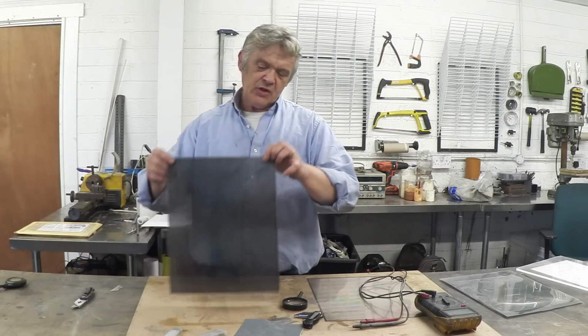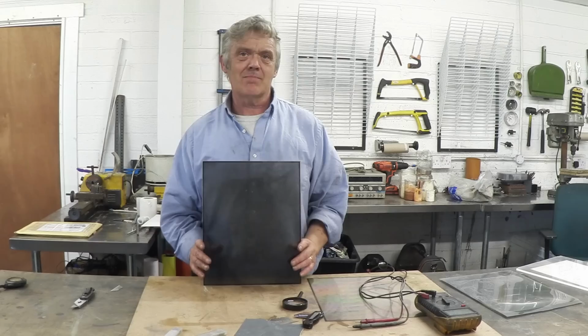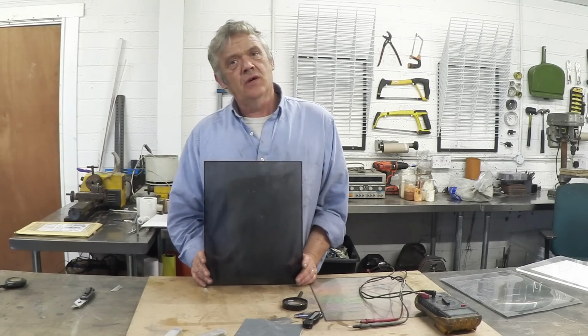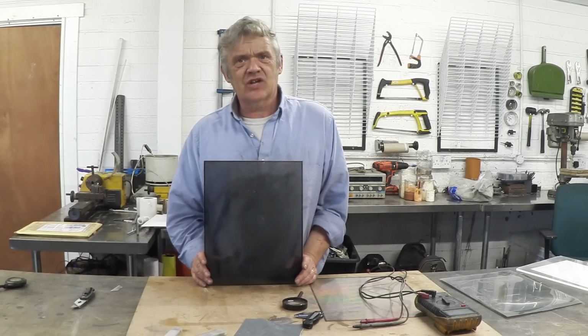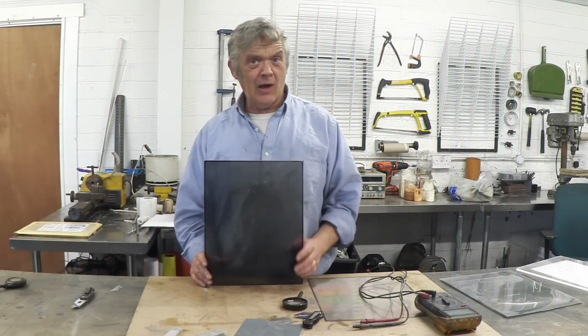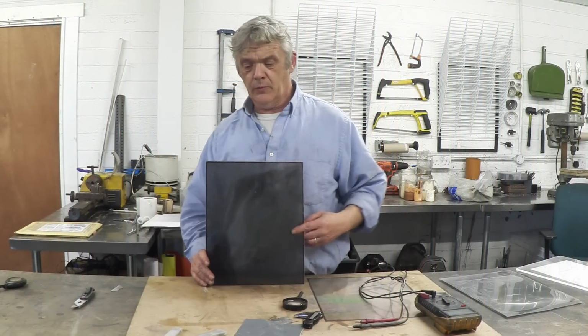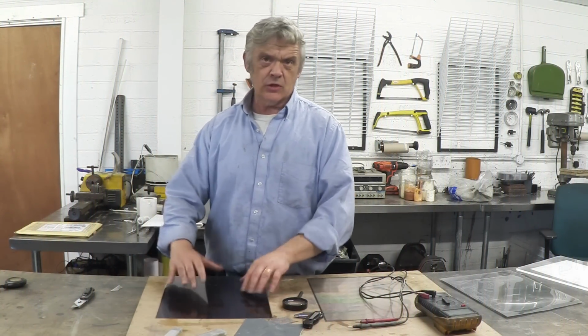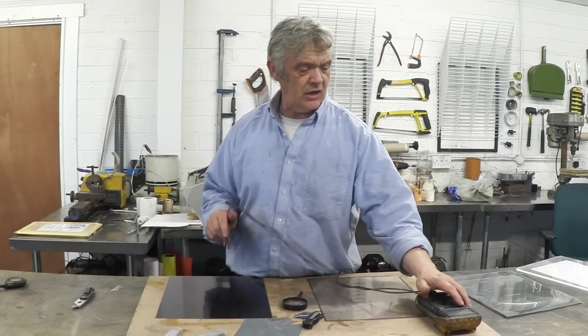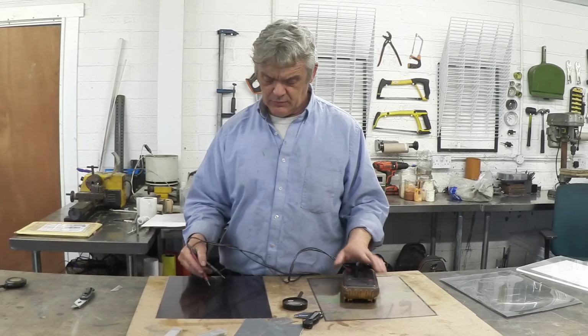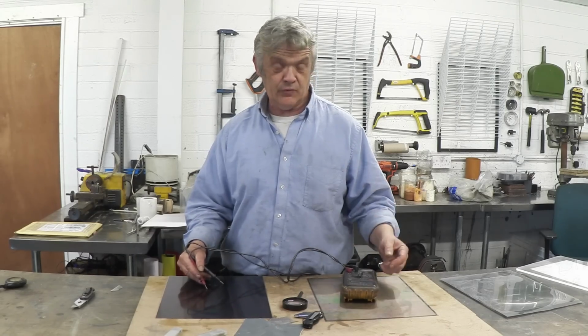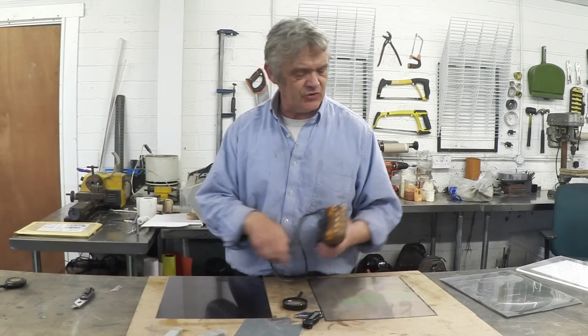This one, what they do with this one is put a black mask on it and then print red, blue and green cells. And it looks like this. After they've done that, what they then do is they print the ITO on the top of that. So right on the top of there is a layer of indium tin oxide. And if we test the resistivity again, we just pop that onto that surface. Sure enough, we get conductivity. It's about 3 ohms a square, something like that.